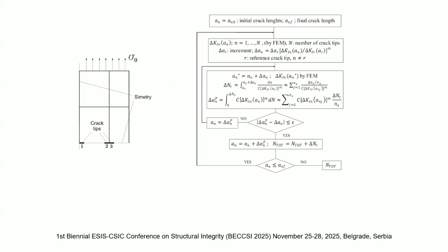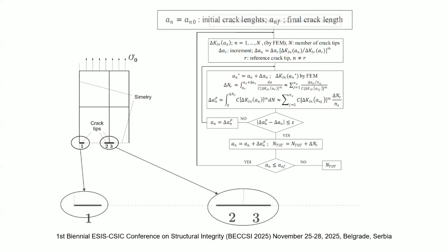And so this is 1/4 of our specimen. We have 3 cracks, but due to symmetry, we have only 1/4, and we can basically have 6 crack tips, but due to symmetry, we consider only 3 crack tips, 1, 2, and 3. And so we show them here. What do we do? Well, at first we should assume initial crack length, and we have taken this from our experiment. So we had the experiment, then we simulated and compared with the experimental result later. So we have to take one crack tip as a reference. So this is in this case tip 1, and for the other 2 tips, then we should see how they interact.